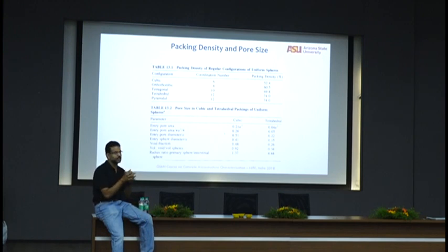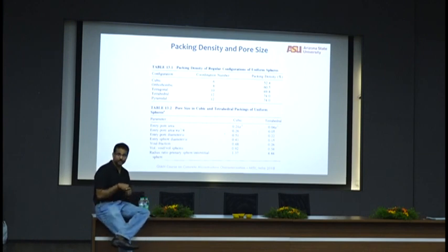For pore structure and pore structure characterization, we will discuss a few techniques maybe tomorrow. For pore structure, how the pore structure is organized is more important than how much void there is for durability. For strength, how much total void there is is important. Right? Strength is inversely proportional to porosity. But for durability, it is the pore sizes that are much more influential. It's not just the porosity, it's the pore sizes.